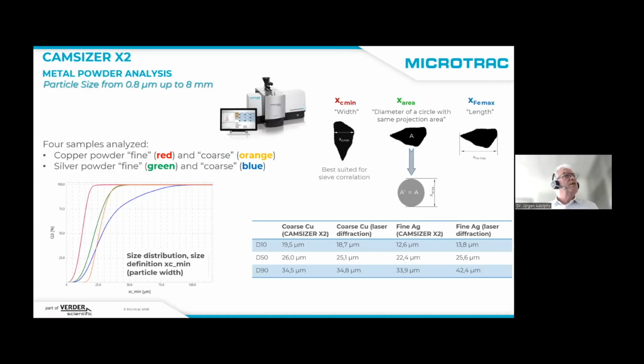The example I will show you here is a Camsizer X2 experiment on metal powders. So the particle size you can determine with the Camsizer X2 are in the range of 0.8 micrometers up to 8 millimeters. And from image analysis, you can get different information. So one is, for example, the minimum width of a particle, which is best suited for sieve correlations, for example. Or you can calculate the area, which is then related to a diameter, which is the same area of a circle or a spherical particle. Or we do have a Feret diameter, which is actually, in this case, the maximum diameter over the entire length, for example.